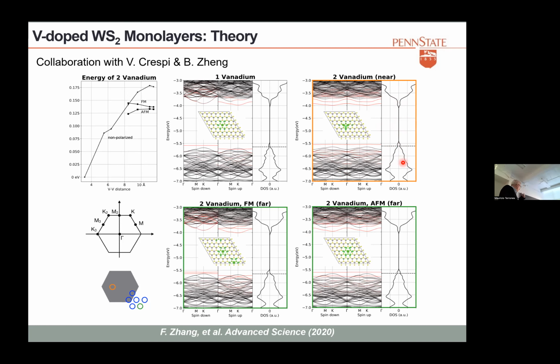so that we could see this ferromagnetism. Again, this is room temperature. We're seeing this in tungsten diselenide, tungsten sulfide, moly sulfide as well, and moly selenide. Everything we have tried with vanadium has worked. Again, it's an interesting phenomenon, and we want to understand a bit more. There's a Korean group, I think Yongki Lee, doing this with tungsten diselenide. They saw something as well. It's an interesting system. They did some MFM. We did MFM, but I don't believe the MFM data.